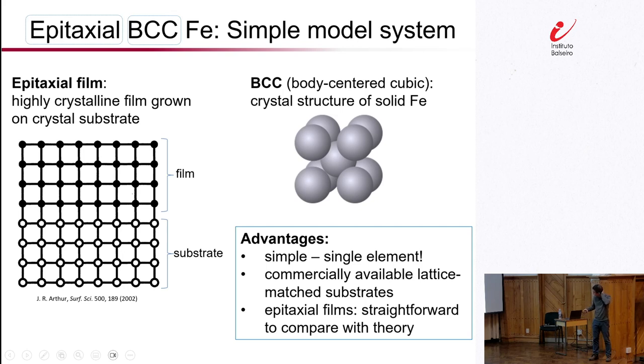And okay, why do we think this is a nice system? Well, first of all, it's simple in the sense that there's only one chemical element, it's just iron, nothing else. So in that sense, we shouldn't have to worry about any kind of complications from, let's say, some kind of chemical inhomogeneity, right? And second, this is quite convenient because it just so happens that we have substrates that we can buy relatively cheaply, not too expensive, that also happen to match with the structure of BCC iron. And finally, by having a nice crystalline epitaxial film, we are then able to compare our experimental results in a more straightforward manner with theoretical and computational predictions.